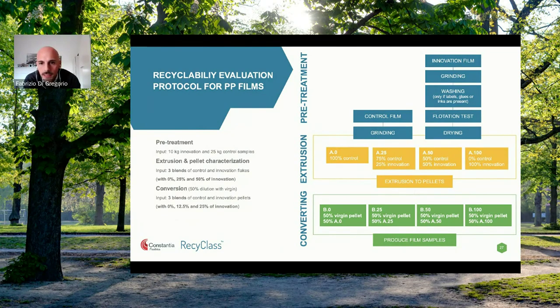After that, the material is further diluted with virgin material for the production of cast film, in the case of PP flexible. After a minimum of 30 minutes of processing or production of films, the films are characterized to check whether, by increasing the share of recycled plastics coming from the sample submitted to the test, there is any specific deviation with respect to the control. This is very interesting because it's a standard procedure able to simulate not only the real recycling process, but also the use of recycled plastics in packaging-to-packaging applications.